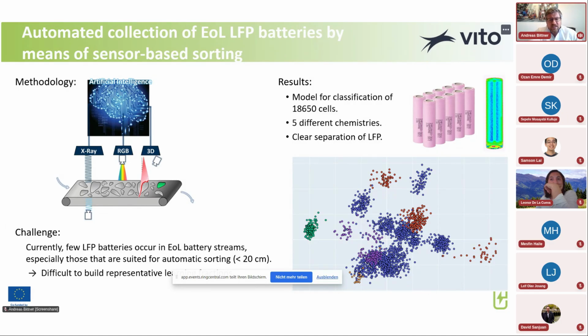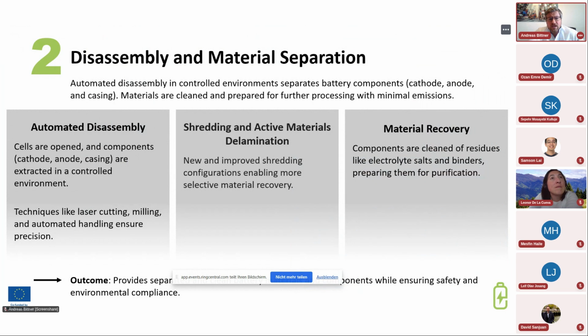The next step is the disassembly and the material or component separation. Therefore, we have two routes. The first route is the automated battery cell disassembly that includes the opening of the battery cell housing, the extraction of the electrode wraps, and then the delamination, the unfolding of the electrode wraps. The second approach is a material selective shredding with an adjusted shredding configuration that enables the recovery of anode concentrates and of cathode concentrates to also use the shredding approach for direct recycling. And both of these routes include also the recovery of the electrolyte solvent and of the electrolyte lithium salt, LiPF6.